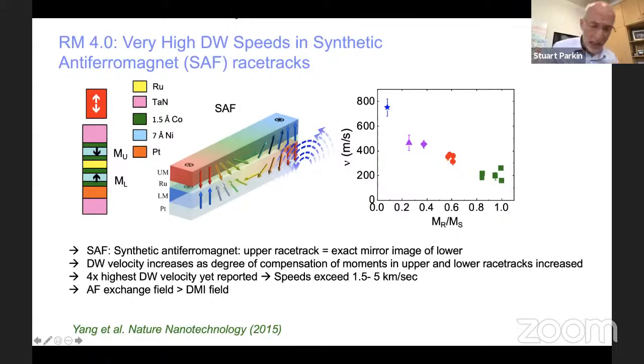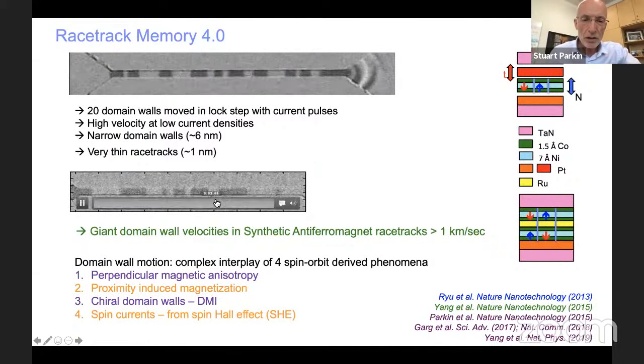So this leads to speeds exceeding 1 kilometer per second for useful currents, and this makes racetrack memory super interesting, because this means you can imagine picosecond time devices where you could move a domain wall 100 nanometers in a picosecond. Very interesting for ultra-fast memory devices. So I just want to show you here.